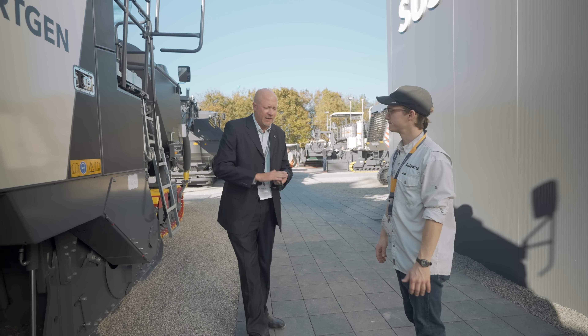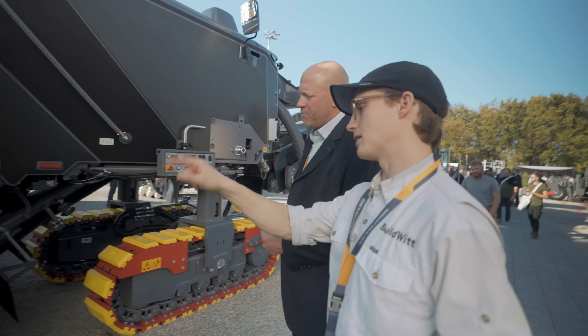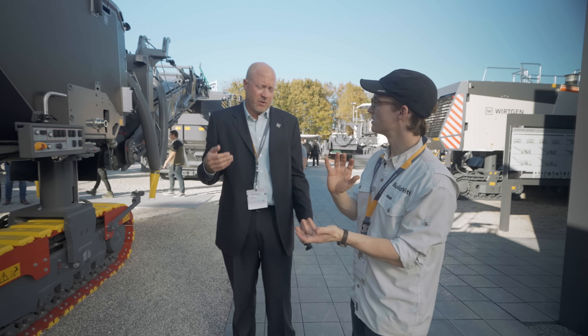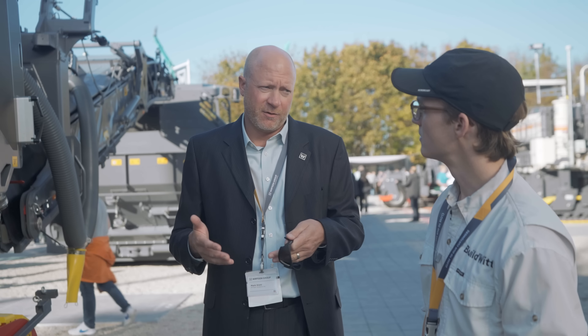The result is a new road with a lifetime of 15 to 20 years added to it using existing material. Regarding cut direction: most mills are up-cut, which is faster for removing material quickly. However, this specific cold in place recycler runs in down-cut mode — because it strikes the asphalt first, it gets better sizing, fracturing the asphalt back into the original particle sizes it was.